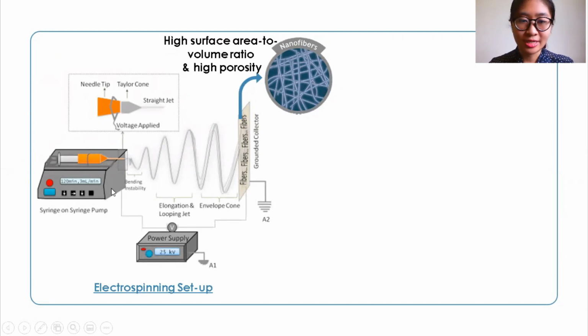So a strong electric field or high voltage is applied between the needle and the collector plate. The polymer solution is pumped through the needle, and an electrified pendant-shaped droplet of polymer solution emerges from the tip of the needle, then deforms into a conical shape known as a Taylor cone. Then a thin polymer jet stream will shoot out and land on the collector plate.